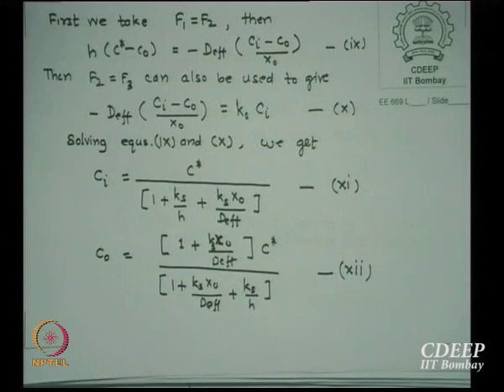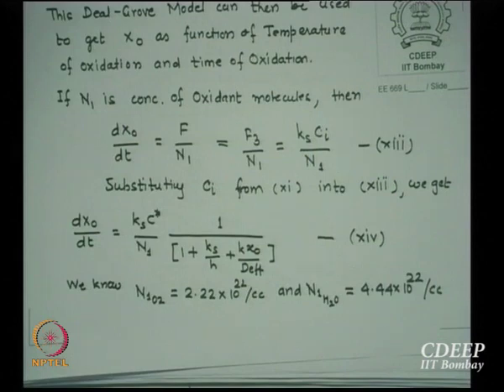So what does the Deal-Grove model say now? What is the oxidation rate? Can anyone suggest? If F is the flux and N is the number available for reaction, then F by N is essentially equal to dx0 by dt. The available flux divided by the available concentration where it can react, the ratio of that is essentially dx0 by dt. So that is the Deal-Grove model, which says if N1 is the concentration of oxidant molecules, then dx0 by dt is F by N1, and F is equal to F1 equal to F2 equal to F3.